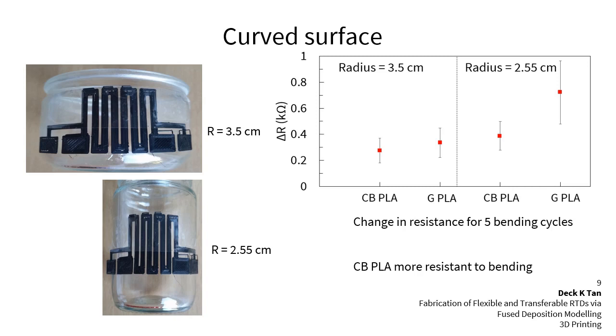The resistance of the sensors was measured first when they were flat, and then when they were bent over the curved surface, and this was bent over 5 cycles in total. So as expected, the resistance of the sensors increased as they were bent over curved surfaces.